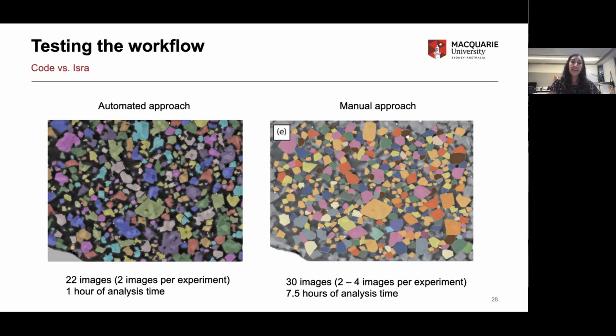And what came out of that was that between 2 expert users, me and my supervisor, we had a 5% difference in the average grain size that we recorded. And that was worse when I then checked what the undergraduates had been up to, and we had up to 20% difference in the average grain size. And that is massive. And that has huge implications in terms of what that means for the grain growth kinetics that we go on to analyze.